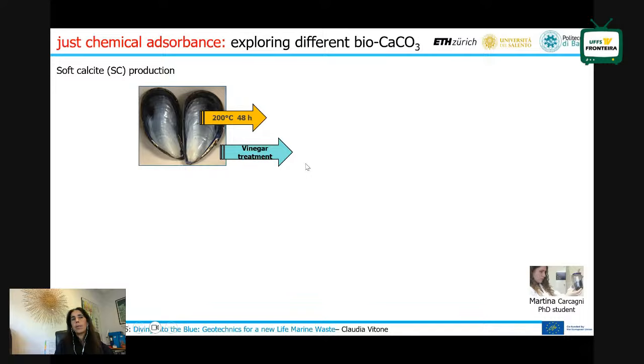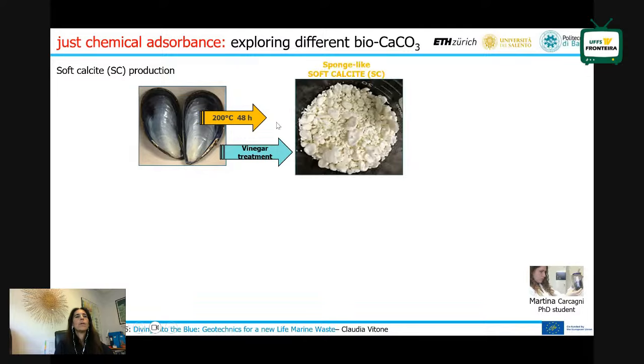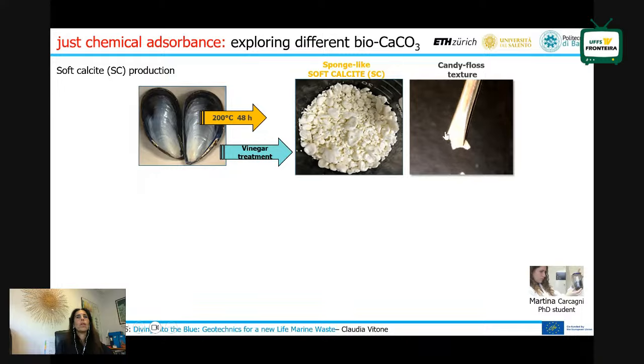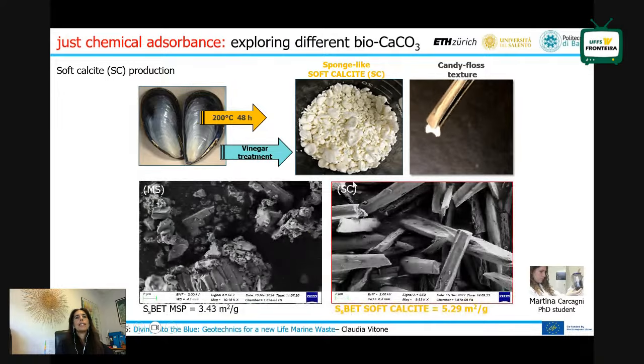So now we are going on in this respect with another PhD work from Martina Carcagni. Martina is essentially working here, trying to chemomechanically modify the shell powder using a vinegar treatment and another thermomechanical treatment to obtain what we call soft calcite, which is essentially pure calcite, this one on the bottom right side, with a quite higher specific surface than the mussel shell powder. Here you can see in comparison the mussel shell powder that I presented so far, and this new product that is obtained trying to isolate the needles of calcite.